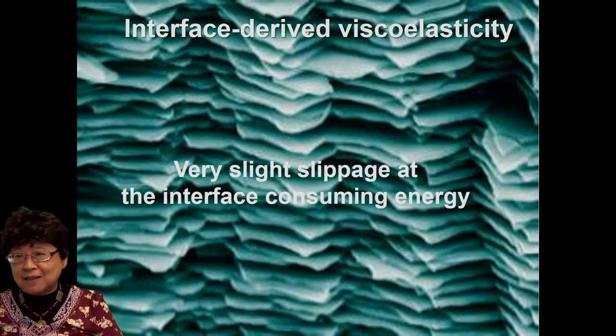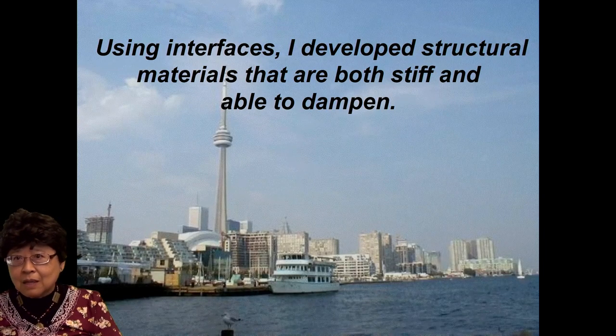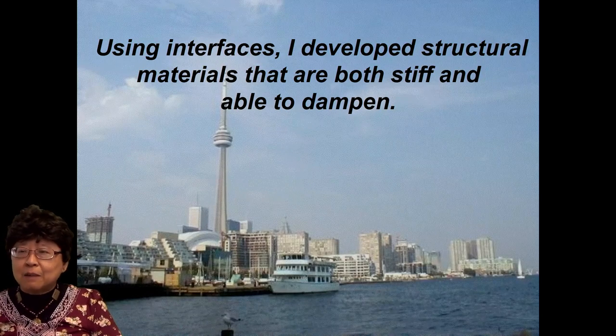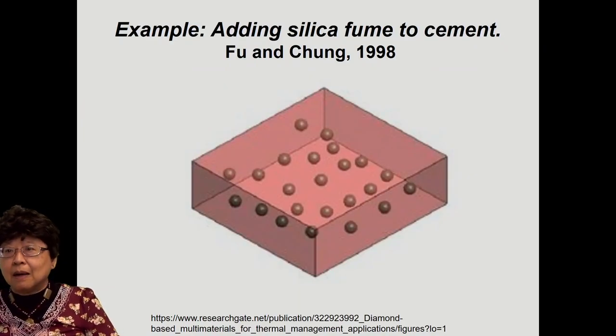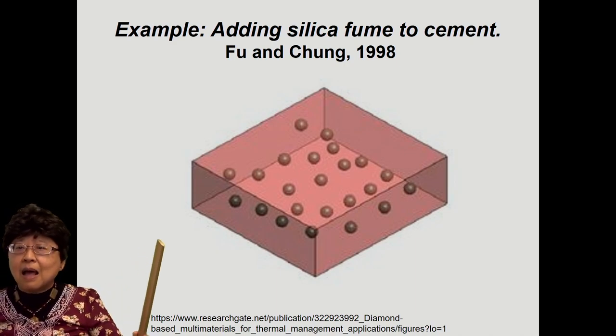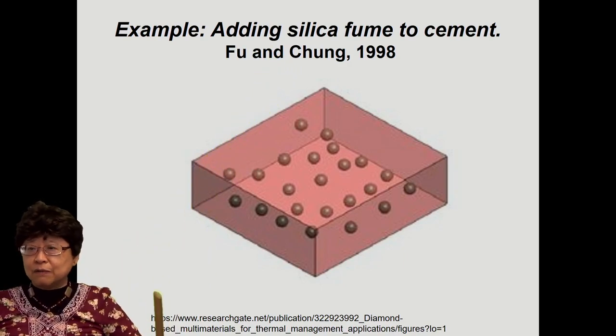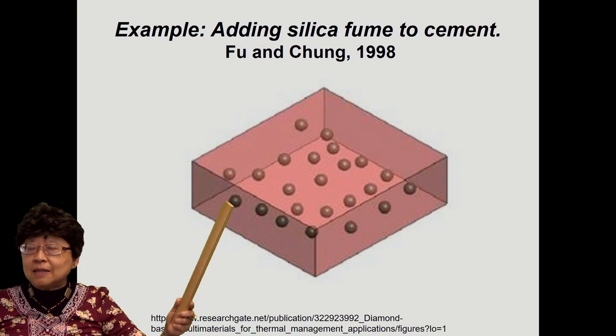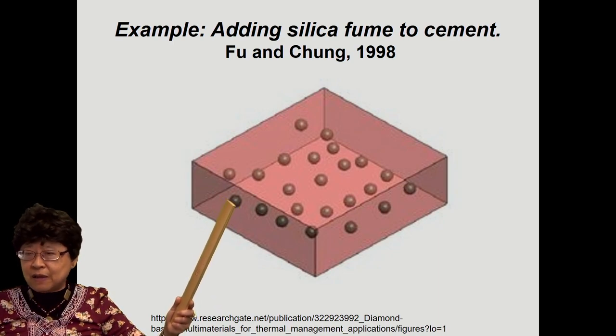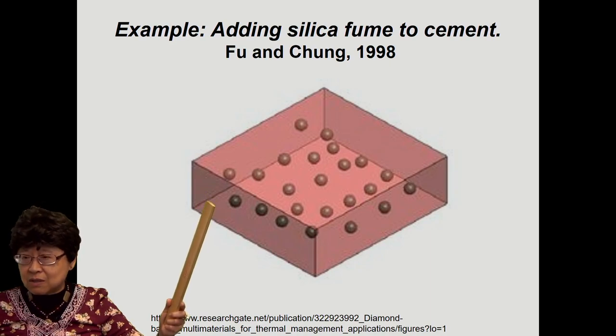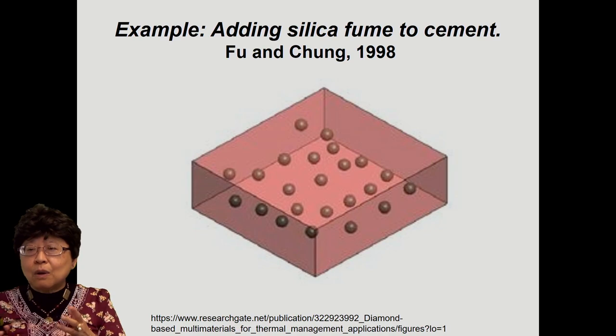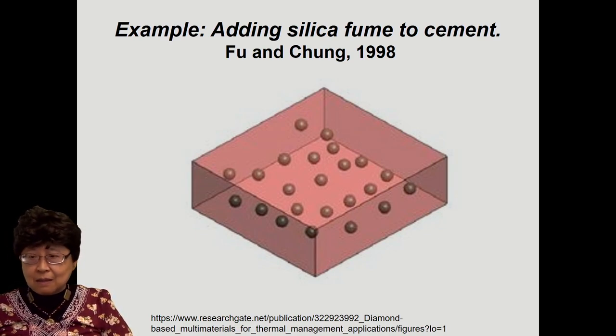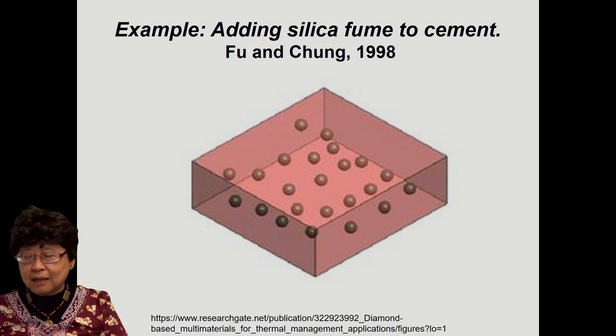And with nano stuff nowadays, you can have a lot of interfaces per unit volume. So using interfaces, I developed structural materials that are both stiff and able to dampen. This is my first example of this phenomenon. I added tiny silica particles called silica fume to cement. Because these are tiny particles, nanoparticles, their introduction gives rise to a lot of interfaces between the particle and the cement matrix. And because of the interface, you have this interface-derived viscoelastic behavior. Thus, the material becomes able to dissipate mechanical energy.